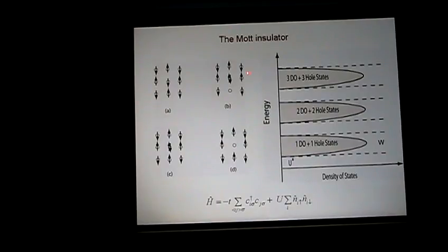And so Mott and Peierls said that perhaps this is caused by the fact that when the electrons try to move next door, you create a double occupancy, and that costs you a lot of Coulomb repulsion energy. So this is basically limiting the conductivity, unless you go just above or just below half-filling by introducing donors or acceptors. And so you create electrically neutral materials, of course, but with doubly occupied sites in this strong coupling picture, or holes.